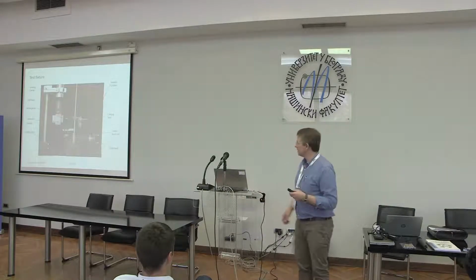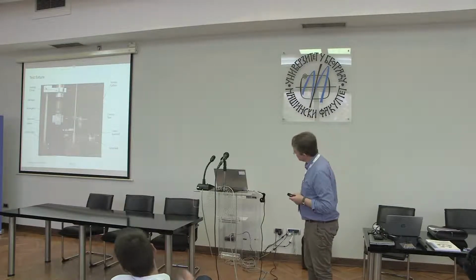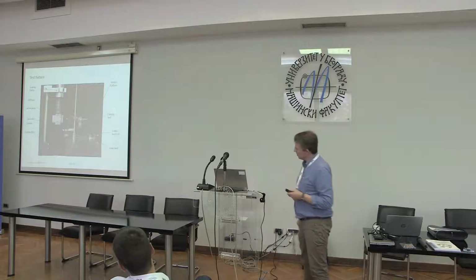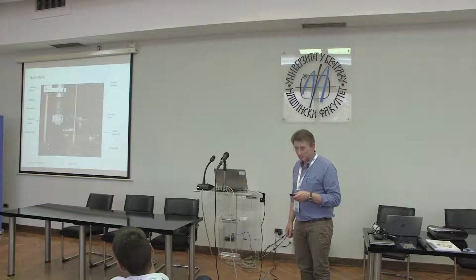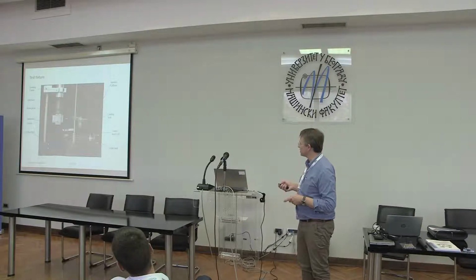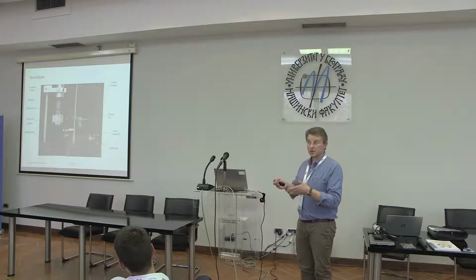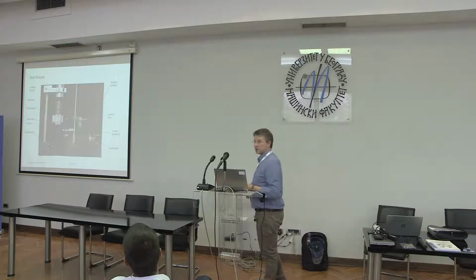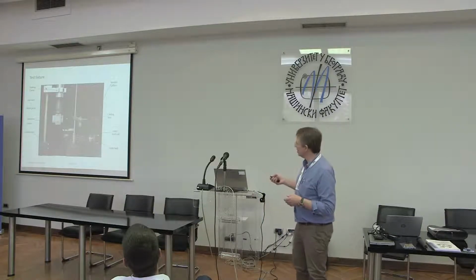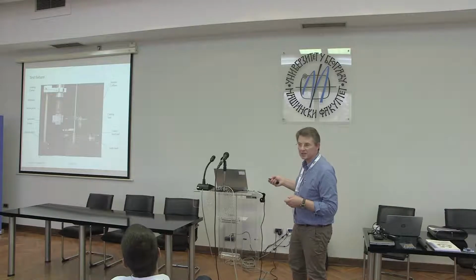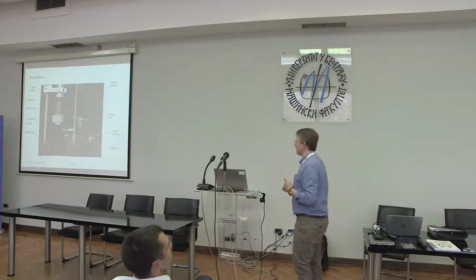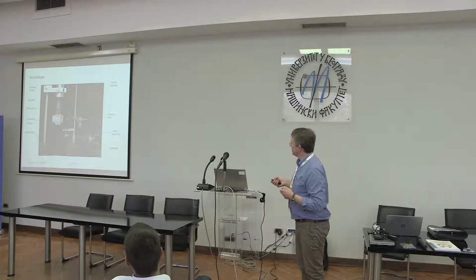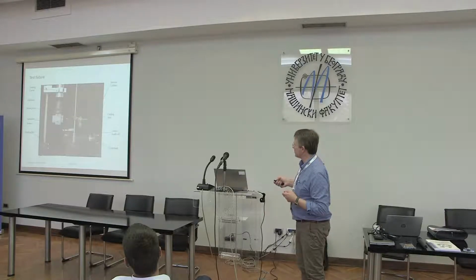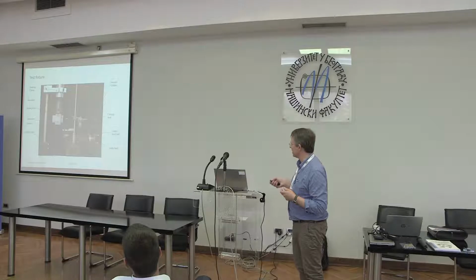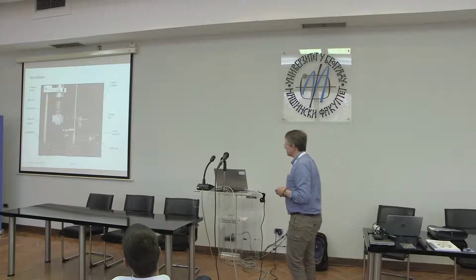And what you do, this is what it looks like. When we first did this on our testing machine, we found that the machine wasn't stiff enough, and our standard high-speed Instron basically flexed too much in this direction to control. Remember, we're trying to control thickness, cut thicknesses down to about 25 microns. So you haven't got to have too much compliance in this to generate that sort of order of magnitude of wobble down at the specimen. So we moved to a very much stiffer system. So this is another machine we had in our lab, so much stiffer, and indeed we also put a guide on to stop any rotation. So that's something you needed to take into account.